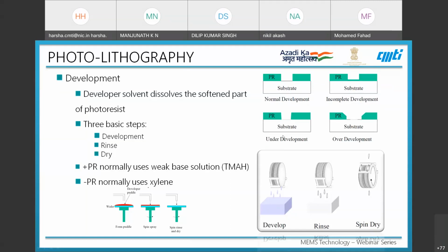If the process is underdeveloped, we see that there is a shape taken by the photoresist, and we may not get a proper coating again. When it is overdeveloped, there is etching of PR on the corners. This will also result in a screw or a cap kind of fixture after the deposition of any metal.